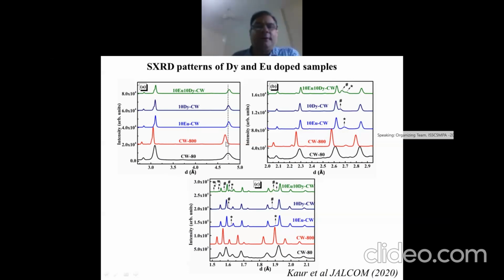So there is some kind of compression which takes place on the crystal lattice when you do heat treatment. When you add rare earth ions like europium or dysprosium, the peaks again shift towards longer d values. So there is a tensile stress arising, and that tensile stress is not due to any replacement of the ions, because the peaks of the cubic oxide phase are detected distinctly. So the two phases coexist, and there is no major substitution of calcium ions in the tetragonal crystal structure. We observe the same features with dysprosium, europium, and also erbium ions.